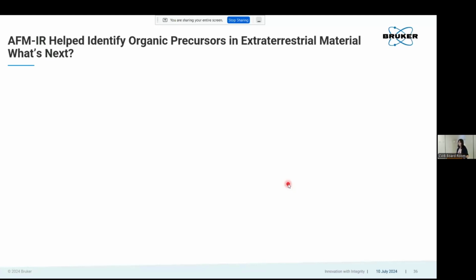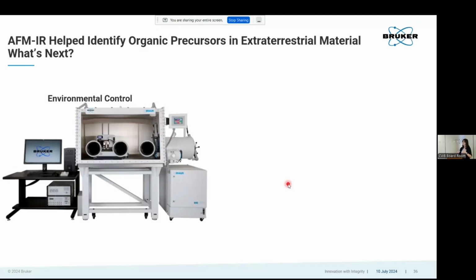So the next steps in terms of this research are getting a system with a large environmental control around it. This is an example of an AFM in a glove box. They want to put an IR system in this glove box such that you can always keep the samples without Earth's atmosphere being exposed to them. They're super, super precious, and it's hard to sometimes see what happens when you take one out of a vacuum environment or out of a non-sensitive environment, and you expose it to all of the oxygen in the air, which can cause it to oxidize and change. And there's all of the carbon in the air as well from us breathing in and out that you try your best to be careful about, but you ultimately can't avoid.